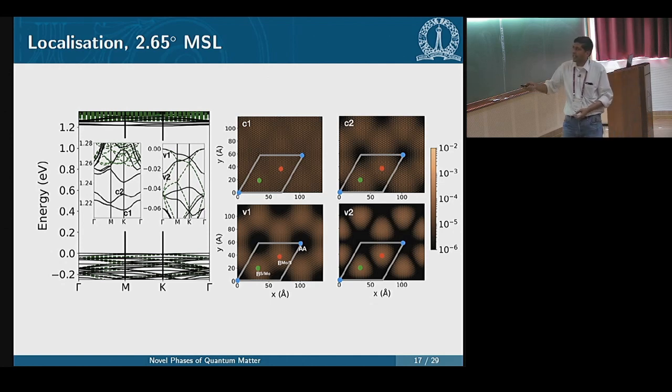Now, if you didn't know the scale here, and you just imagine these to be two sites in the graphene lattice, the first two bands are basically forming the graphene-like dispersion, which is the reason why you see a graphene-like dispersion over here and a crossing at K. So obviously, unless you put some strain on it or do something else, you're not going to be able to open a gap here, for the same reason as you would not be able to open a gap in graphene, right? But on the other hand, you see that the conduction bands are completely delocalized, right? They're just everywhere.